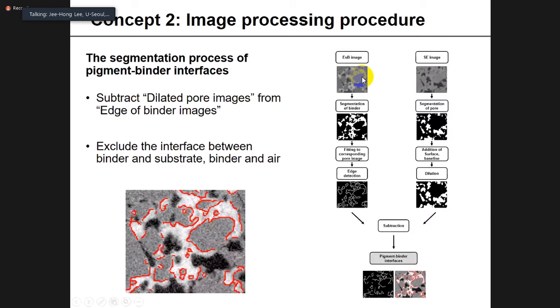Here you can see how we did the image processing procedure. We get the edges of binder, and we get the pore here, and we actually don't need to make it edges, just dilate it to get better overlaying of the interfaces. If you subtract it, then you get these pigment-binder interfaces. Here you can see the overlay image of the segmented pigment-binder interfaces on the actual coating layer, and you can see that it fits the image quite well. Also, the addition of the surface baseline is included because we should exclude the interface between binder and substrate, and also between binder and air.